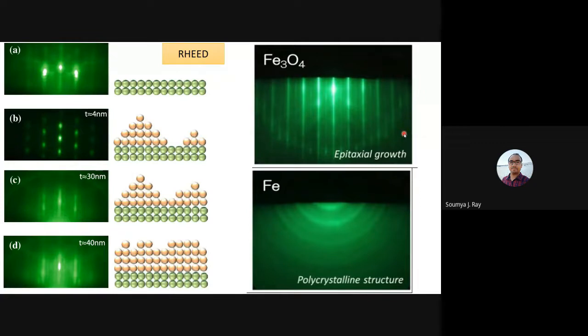Epitaxial means that the structure at the bottom and the structure on top have a similar crystallography, and the lattice spacings are also similar, which means there is negligible interfacial strain, like one unit falling on top of another exactly at the same position. That way you get higher diffracted intensity, and that is why you get these sharp bright lines. But here, since it's polycrystalline, the degree of crystallinity is low, so you get an average intensity, and only a few lines appear.